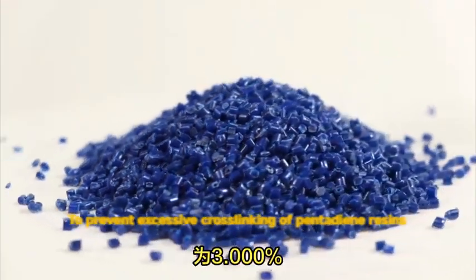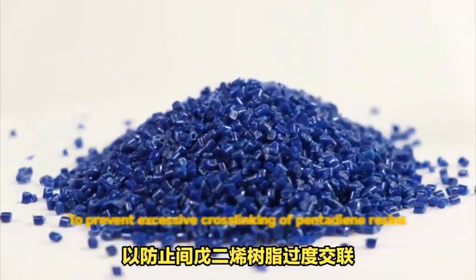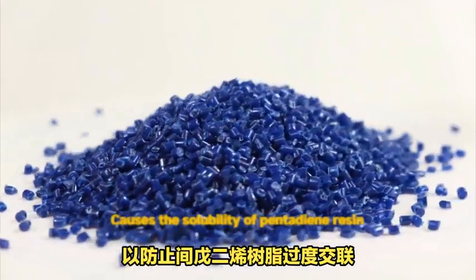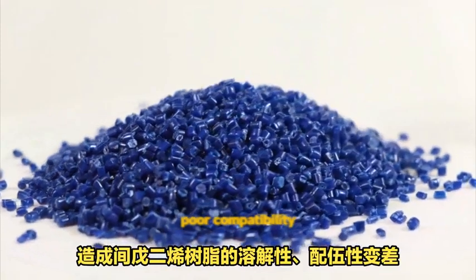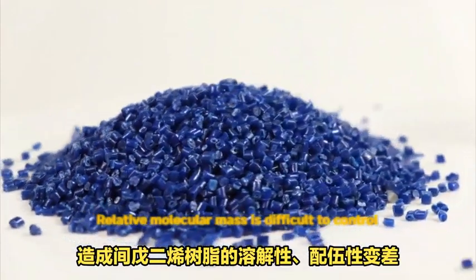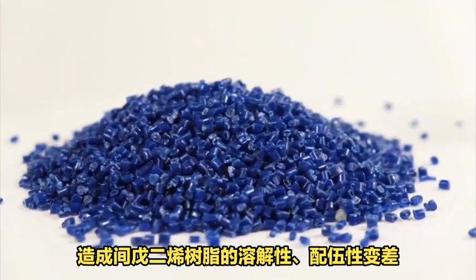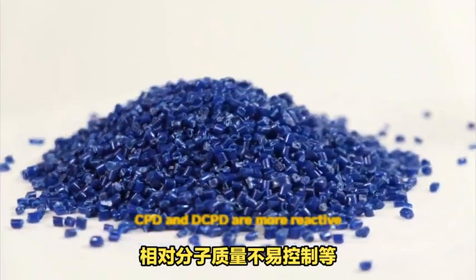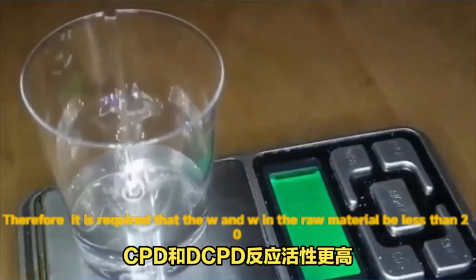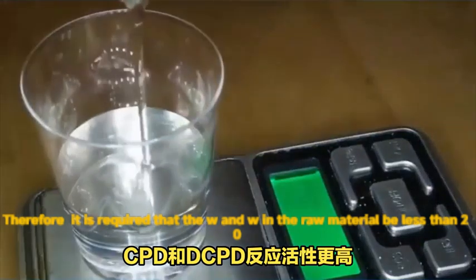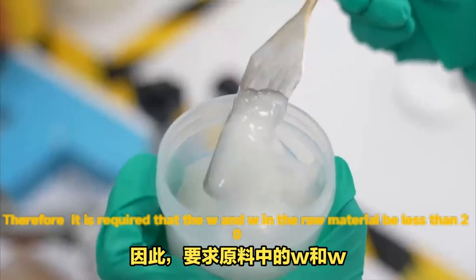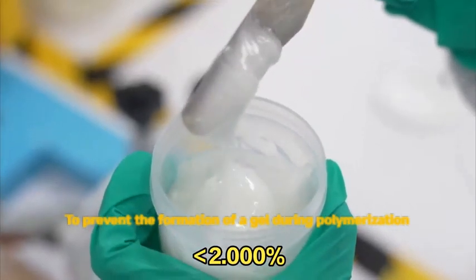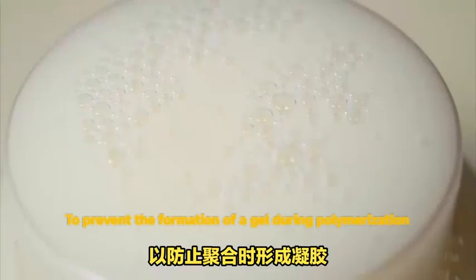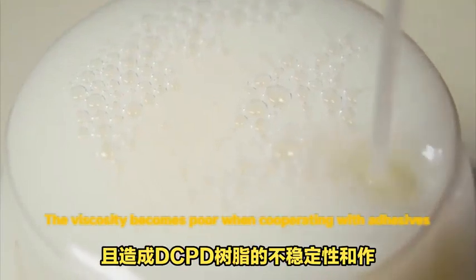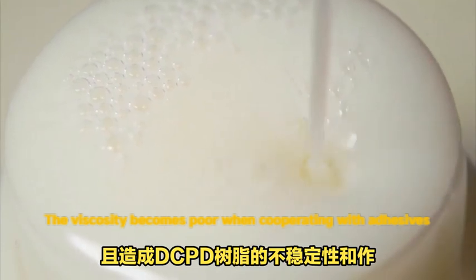This is to prevent excessive cross-linking of the resin, which causes poor solubility and poor compatibility, and makes the relative molecular mass difficult to control. CPD and DCPD are more reactive. Therefore, the CPD and DCPD in the raw materials are required to be less than 2.0% to prevent gel formation during polymerization, which causes instability of the resin, and poor viscosity when blended with adhesives.